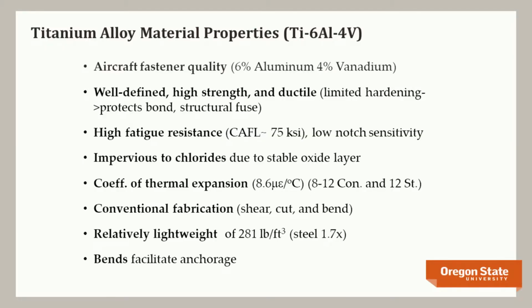So here's kind of an overview of the material properties. We're using not pure titanium. We're actually using an alloy. This is the same material that's typically going into aircraft fasteners at Boeing or Airbus. It's got 6% aluminum, 4% vanadium, and that's the spice that makes it work. It has well-defined high strength, and it's ductile. Right? We can limit the strain hardening effects, and you can think of it as kind of an ideal structural fuse. So if you're looking to force protect elements, it's a great material.